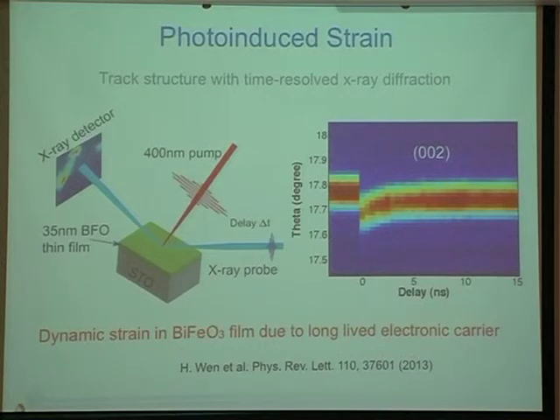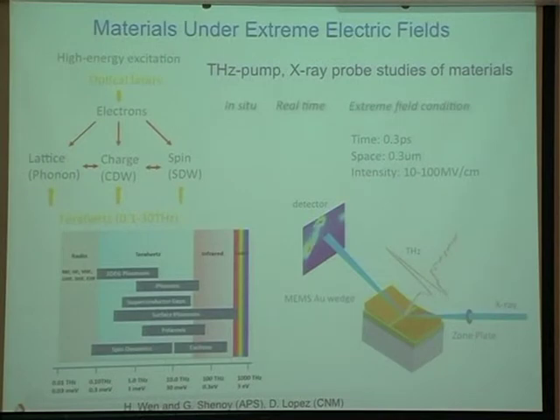But the challenge with optical pumping is that you put in a whole lot of power with this laser light. And so you do a whole lot of heating, which of course you don't want. That's a challenge because if you think of it from an energy point of view, it means only a tiny fraction of energy is going into exciting the mode you want, and all the rest is just heating it. So that's why the idea of mode-selected pumping is very interesting. If you could come in and say, pump a phonon, or pump across a gap, excitons, polaritons, you can pick whatever is your favorite, this could be a very interesting modality for trying to control materials in new ways.